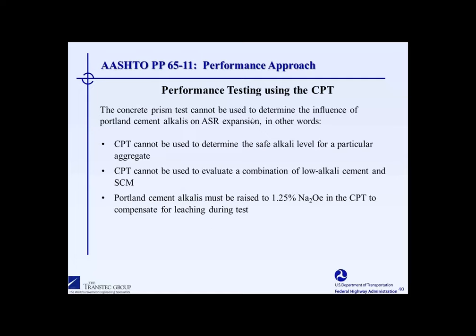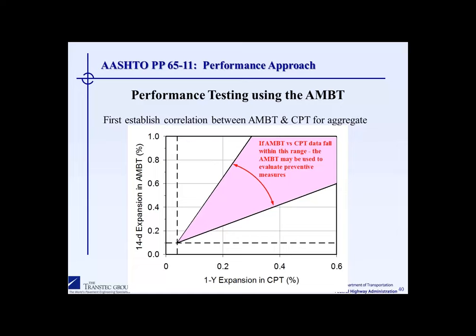In terms of using it as a performance test, I'm just highlighting some of the same issues I already discussed. It can't be used to evaluate alkali thresholds because of leaching. And it can't be used to look at low alkali cement in combination with SCMs for the same reason. We do boost the alkalis to 1.25% alkalis, as is done in the concrete prism test. And this is intended to provide a high enough alkali content to begin with that there will be sufficient alkalis in the prism during the course of the test to trigger expansion.